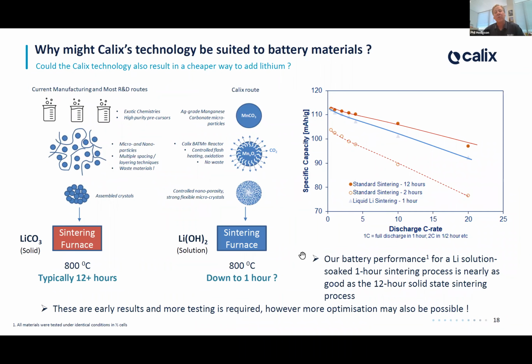The second little piece I want to talk about is, well, it's great to produce your raw crystal, but remember, I said before, you've got to get your lithium into it. And traditionally, what the current methods use are taking what's called a lithium carbonate, which is a solid. You mix that with your crystals and you shove it in a furnace for 12 hours. And it could be much longer than 12 hours, 12 minimum. And this route here, why we're interested in the nanoporosity, apart from the strength of the crystals we're making and that controlled porosity, is we can use a liquid doping solution here. So we start with a lithium hydroxide, and we're trying to get the sintering stage down as much as we can. And so where are we at with that process?